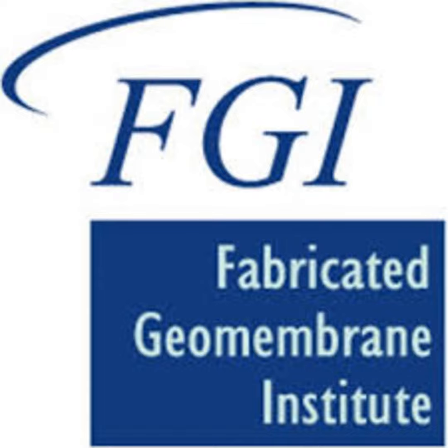So if your goal is to have a really well-controlled interface strength, sure, but my opinion is that's not a great design, because there would be no reason to use a high peel strength GCL that is more expensive from the manufacturing process with a low textured geomembrane, because you're just not getting any of the benefit from that GCL. So those are my thoughts on that question.